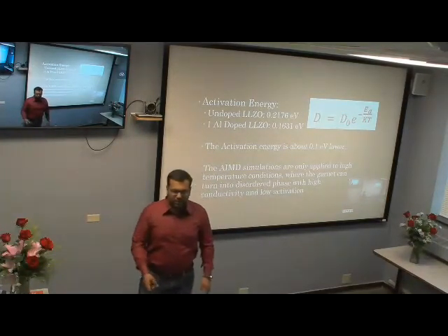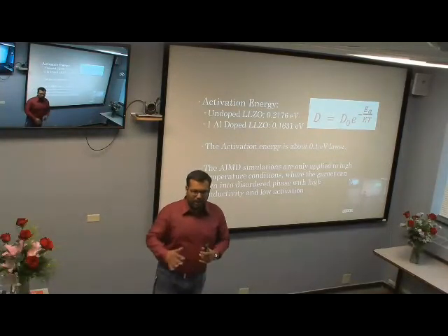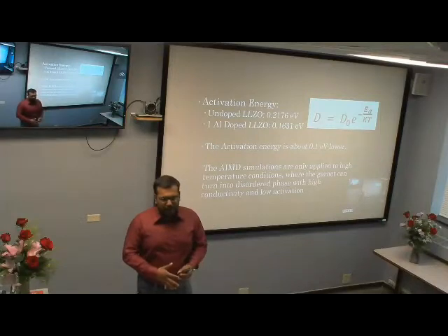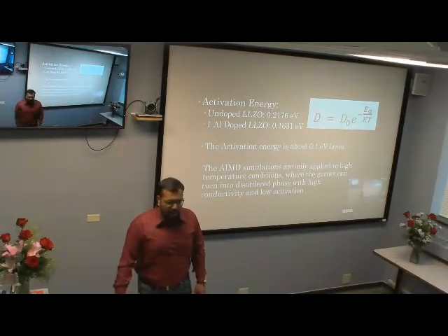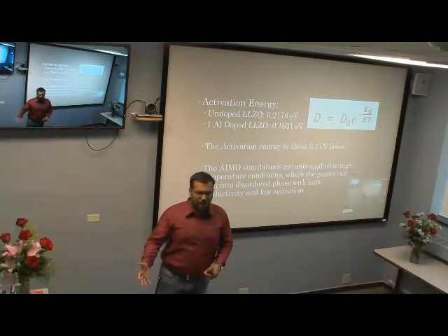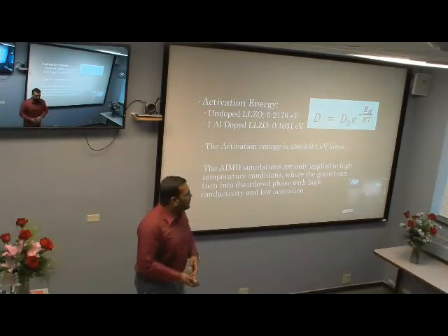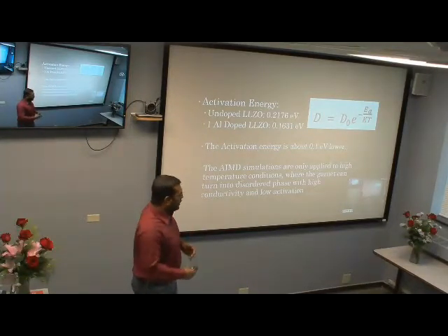There are a few reasons, like we have considered so many standard structures, not experimental, and we have calculated the diffusivity at very high temperatures and then extrapolated it. That's not normal. In our experimental cases, those are run at room temperatures. So that is the reason why our activation energy is lower than the experimental value.